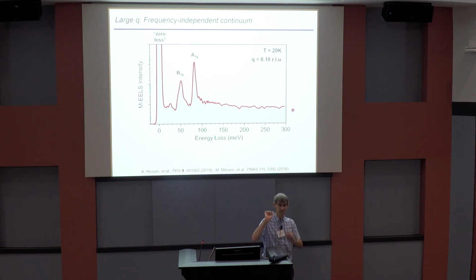This is not some little tiny wiggle in an STM science paper. This is the dominant contribution to the charge susceptibility of the cuprates. 99% of the spectral weight is contained in this continuum. It's not a tiny effect. It is highly, highly reproducible. We've seen it hundreds of times over the last 5 years.